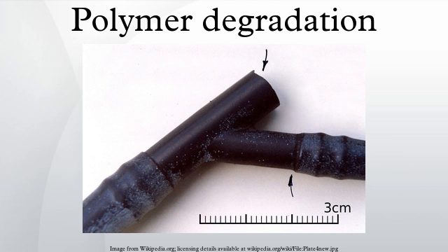Ozonolysis. Cracks can be formed in many different elastomers by ozone attack. Tiny traces of the gas in the air will attack double bonds in rubber chains, with natural rubber, polybutadiene, styrene butadiene rubber and NBR being most sensitive to degradation. Ozone cracks form in products under tension, but the critical strain is very small.